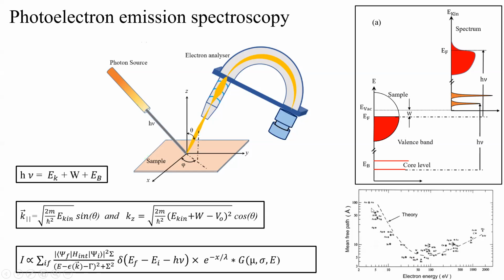Now this is basically the mean free path as a function of electron energy. As you can see, it follows a somewhat parabola type of shape. It's not a parabola, but somewhat parabola still. It shows a minimum value within this 50 to 100 eV range, and in this range the mean free path is around 5 angstrom. Because of this mean free path, the technique that we use is very surface sensitive. If there is anything on the surface, just one layer of oxygen or something else, it will make things worse. We won't be able to see anything from your sample. We'll basically get the counts from the upper impurity layer.